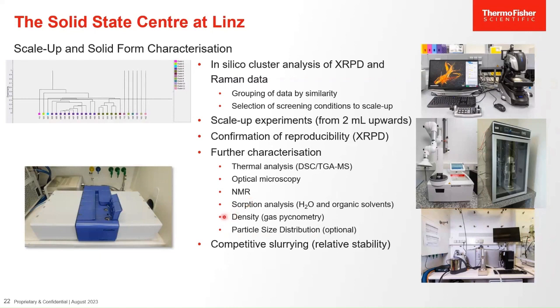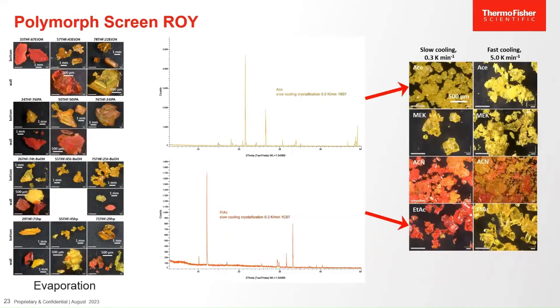In some cases, it may be interesting to look at the true density of your solids. We have gas pycnometry for this. Density can also be used as a measure of relative stability, so in cases where there is doubt, this may be useful. And we can also look at particle size distribution, though this is normally not part of our screening activities. It's more something that we would use for crystallization process development. And then the final step, determining the relative stability of our polymorphs, we use competitive slurrying.